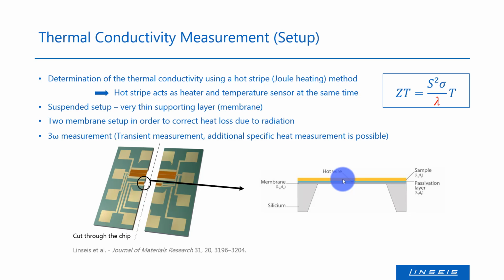The silicon rim acts as a heatsink, and because of the large aspect ratio between length and width, we get a nearly ideal 1D heat flux from the heater in the middle to the surrounding rim. As we know the geometry of the membrane, we can calculate the thermal conductance of the membrane, or membrane plus sample setup, by measuring the occurring temperature rise of the hot wire, independent of the applied heating power.